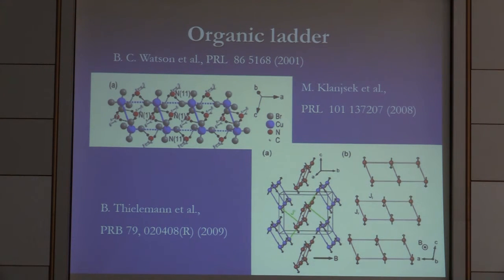So we know this exchange. For this ladder, this is about 12 Kelvin, this exchange is about 4 Kelvin, and this exchange between ladders is about 50 millikelvin. So for a whole range of temperature, the approximation of having independent ladders is extremely well justified. As long as I don't go below around 100 millikelvin, I can really consider this material to be in a one-dimensional situation.